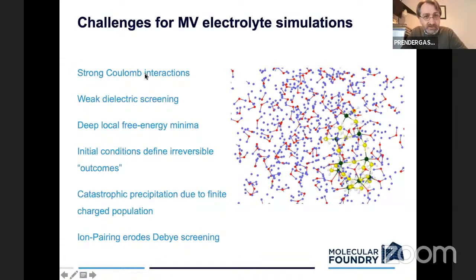So you have very strong Coulomb interactions, weak dielectric screening. There may be quite deep local free energy minima that you can get trapped in as you do your molecular dynamics. And so your initial conditions can lead to some irreversible outcomes. You basically will only explore a very narrow region of space within the free energy landscape.